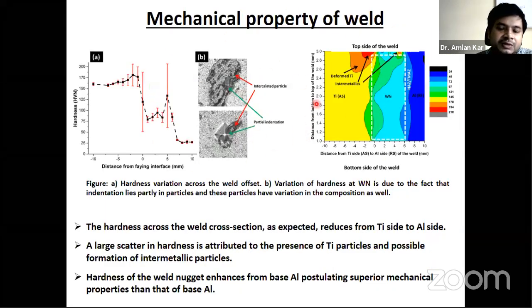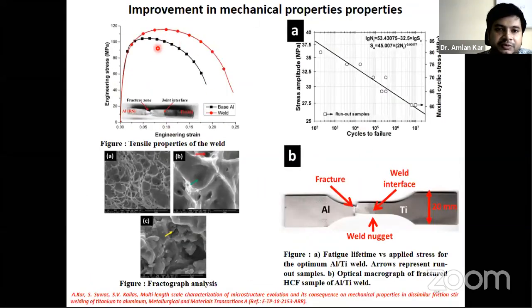So this is the common phenomenon in the case of welding. It does not have much relevance in the case of topology, but one thing I am showing is a different kind of intercalated structure, where the matrix is very ductile because it consists of aluminum, which is very much recrystallized, and this is the particle. Because of this particle distribution, you can see there is scatter in the hardness values. And this scatter is not homogeneous, it is heterogeneous because it depends on the particle distribution as well. And we have observed a very good mechanical property.